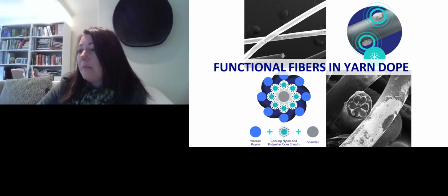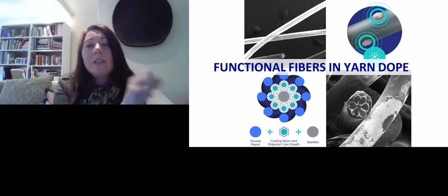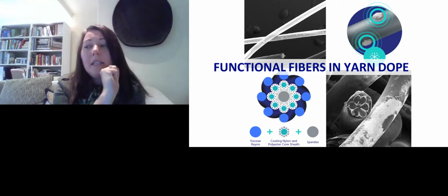There is a microbiological analysis that is run, and the main test that you use is AATCC 100. And when you state to the mill, okay, I want you to use this testing standard, you need to also state which type of bacteria you want them to test for.